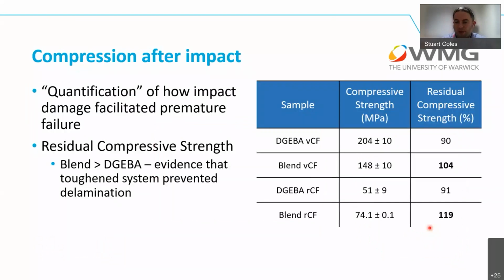What we actually looked at was the compressive strength, before and after impact. So what was that residual compressive strength? And we found that in both cases, the blended materials actually had a higher residual compressive strength after impact, that they were effectively able to repair and improve some of that compression. They were mitigating some of the damage that was caused by that impact and that barely visible impact damage. Effectively, we had a toughened system. We were preventing some of the delamination that was occurring in the brittle DGEBA-only systems.